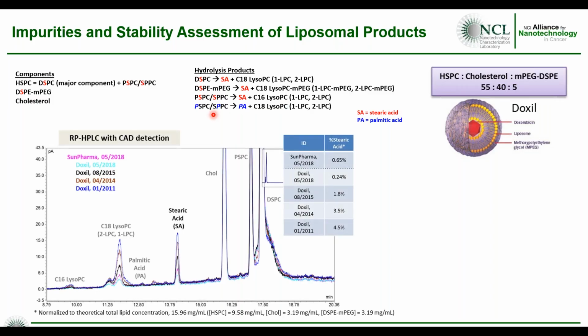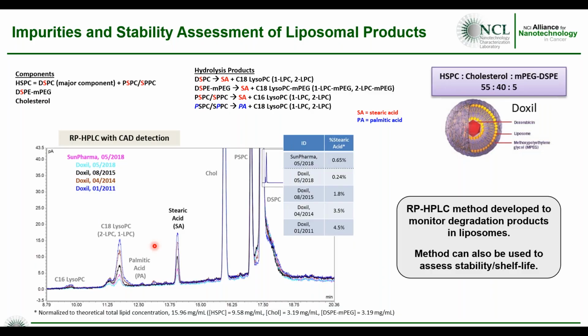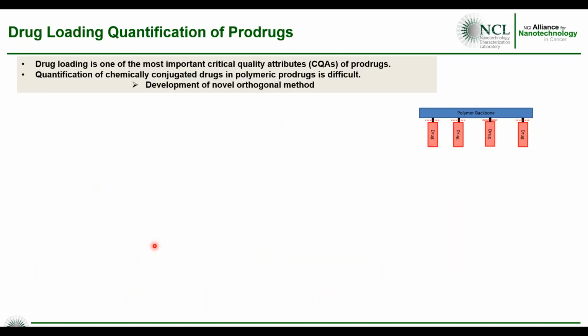And for that, again, we came up with an HPLC with CAD detection method to look at the free fatty acids. In this case, we're looking at 4 batches of Doxil, each with different expiration dates, as well as the Doxil analogs made by Sun Pharma. And you can see the stearic acid peak here. And as expected, the older lot has more stearic acid, the more recent has less. So you can use this methodology to track the free fatty acid. You can also use this to track the corresponding lyso-PCs. So that's a good mass balance check. So it's a good way to assess stability and shelf life for these liposomal products.